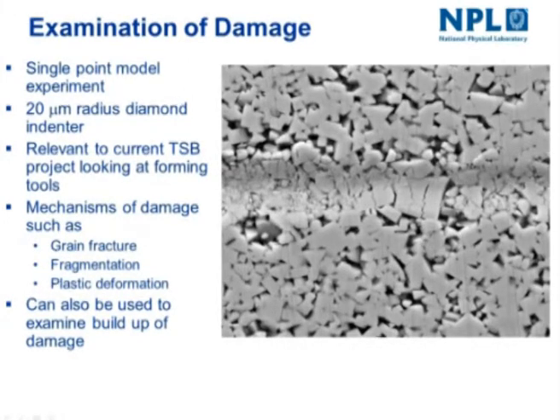TSB project looking at forming tools, and what we were trying to do was replicate the damage that we were getting from scratching in the application. And we saw mechanisms such as grain fracture, so you can see a big grain here which is fractured, fragmentation. There are areas where those grains are fragmented, and not in this diagram, but you can also see a lot of evidence for plastic deformation, these carbide grains. And the other thing that we do is repeated scratching, so you could look at the build-up of damage with a progression of the test.